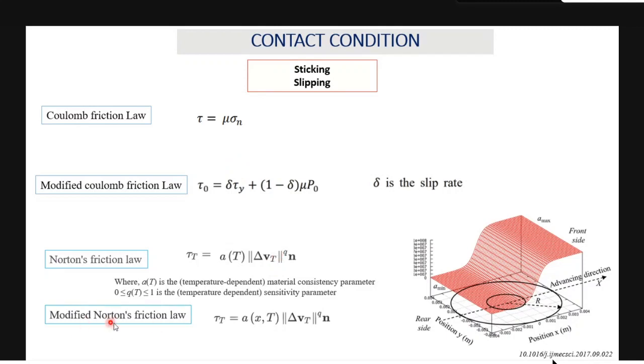So a modified Norton friction law evolved, where the A parameter is a function of the position. In this figure, you can see that this A value varies with respect to the tool center axis to the periphery. Here you can see that you are having more pressure in the tool front, so you are having a maximum value of A, and a lower value of A in the tool rear. So these can be accommodated when we go for modified Norton friction law.